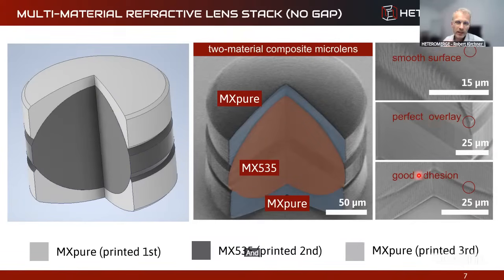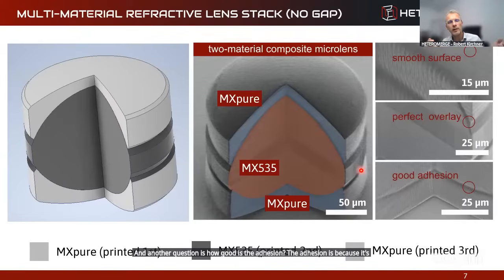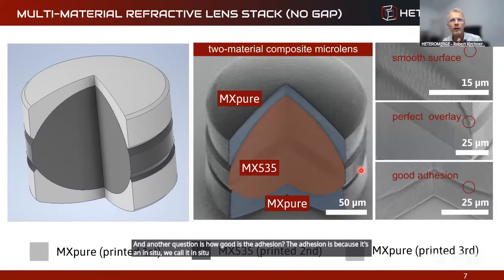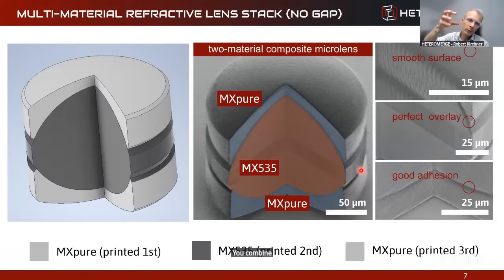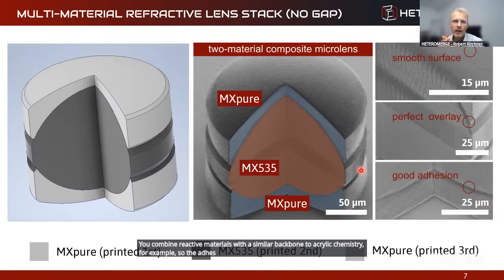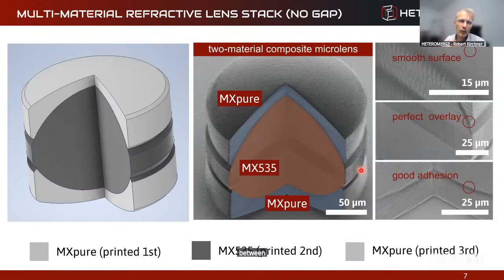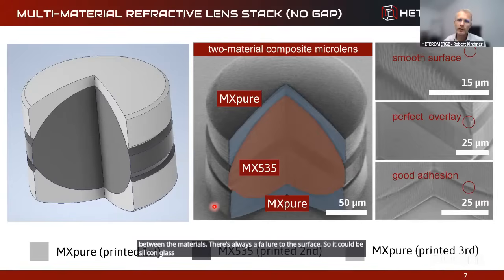And another question is, how good is the adhesion? The adhesion is, because it's in situ, we call it in situ swapping of the material, very high because you bring very reactive surfaces. You combine reactive materials with a similar backbone, the acrylic chemistry, for example. So the adhesion is very good. Actually, we never saw a failure between the materials. There's always a failure to the surface. So it could be silicon glass, but it never fails between the materials. And it doesn't matter whether they're in direct contact or whether they're stacked with some spacers.